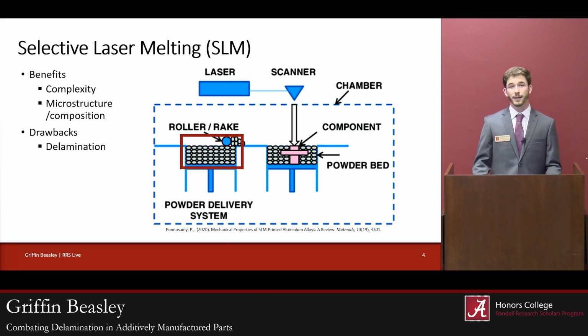In addition, by finely tuning the laser's output, microstructures can be intentionally created during the process, which limits the need for post-process heat treatment. Also, chemical composition is almost perfectly maintained throughout the process. This means that the chemical composition of the powder that is put in at the beginning almost exactly matches the chemical composition of the finished part, which is another quality that is often not found in other manufacturing styles.